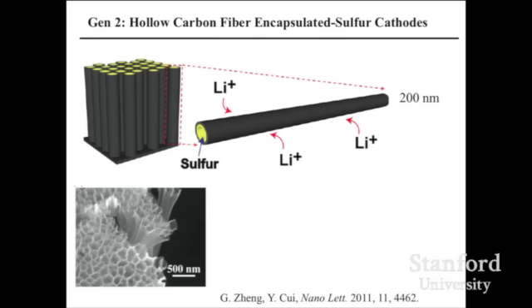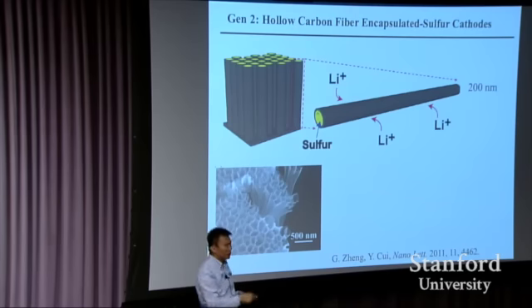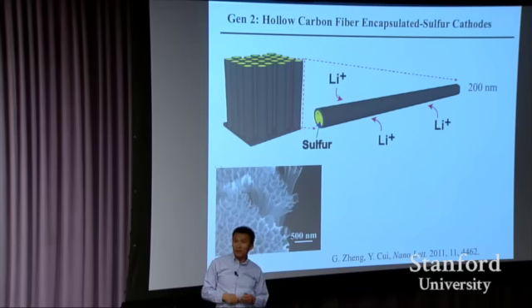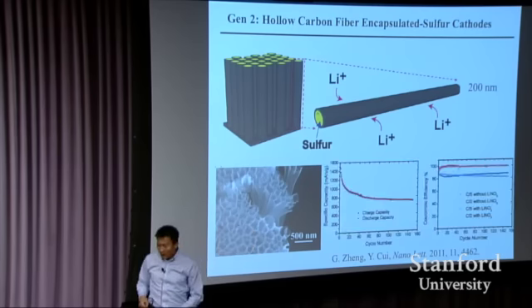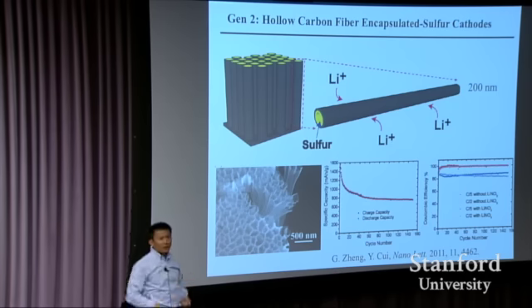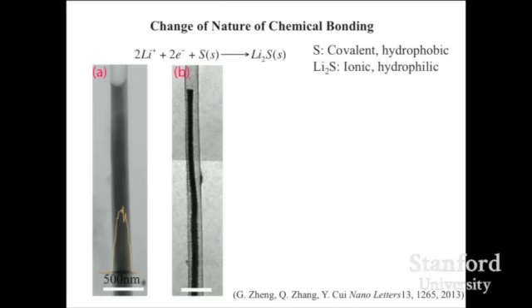When Wesley joined my group, we started to develop this hollow carbon fiber to embed the sulfur inside. Sulfur has volume expansion. Let's embed it inside, leave some empty space right there, just like silicon. The expansion was inside. They are captured by this hollow carbon fiber, only leaking out the polysulfide from two ends. By doing this, we at least can improve the performance quite a bit. Yes, it does, but it still decays. So then we looked at this in detail to see what's happening. And once Wesley started to show me this image, it became very clear.